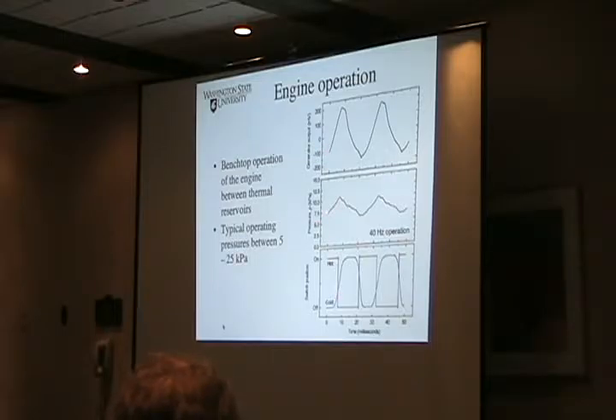So we do this with our little piezoelectric generator. We apply heat at 40 hertz. We have the thing oscillate. You see a mechanical output. And typically we operate at pressure somewhere between 5 and 25 kPa. So we have these little millimeter across, micron thick, with nanostructured bits underneath, moving heat in and out, heating, cooling, generating electrical power. So it's a tiny little external combustion engine.